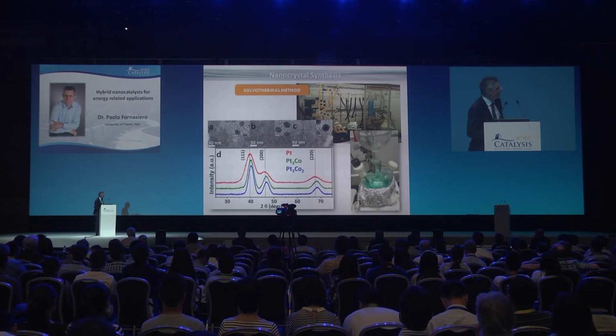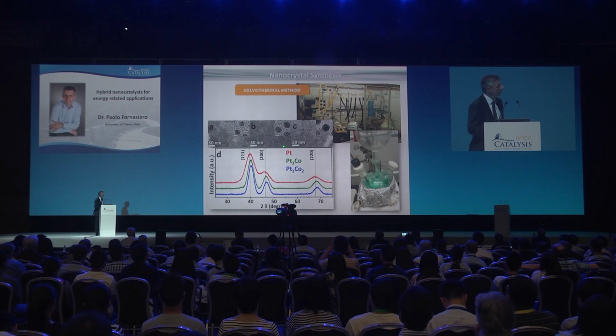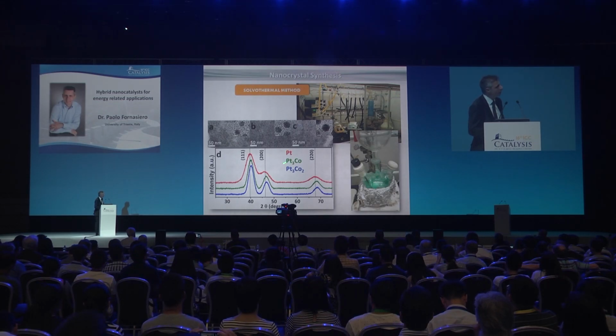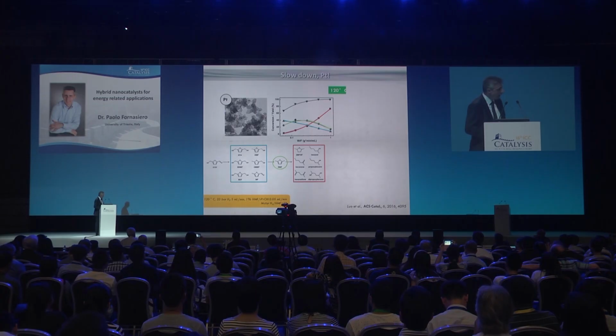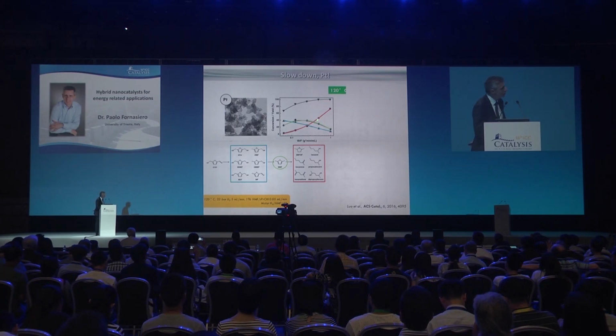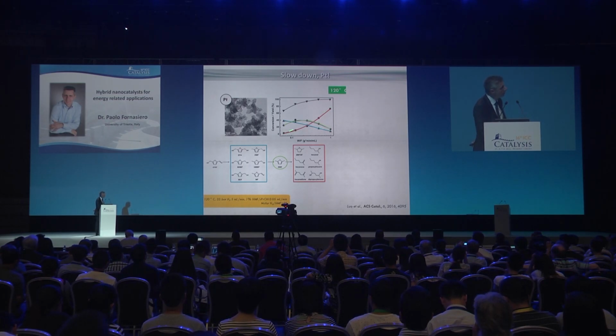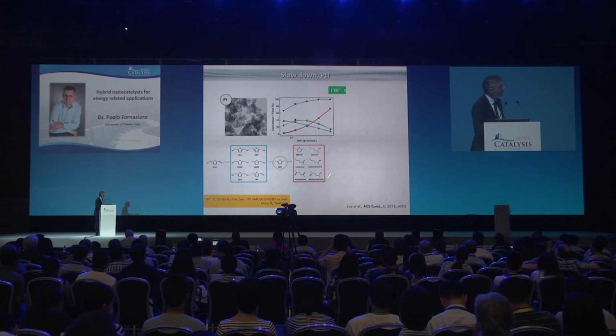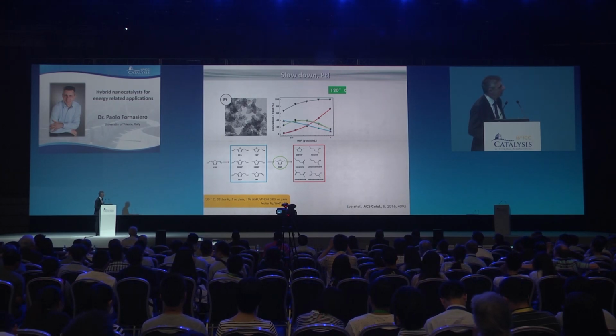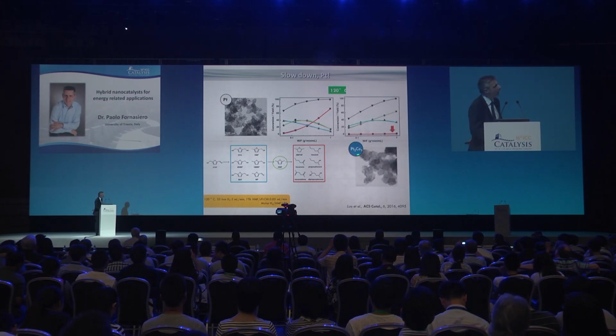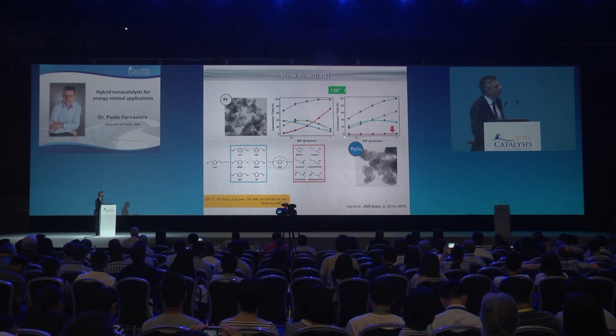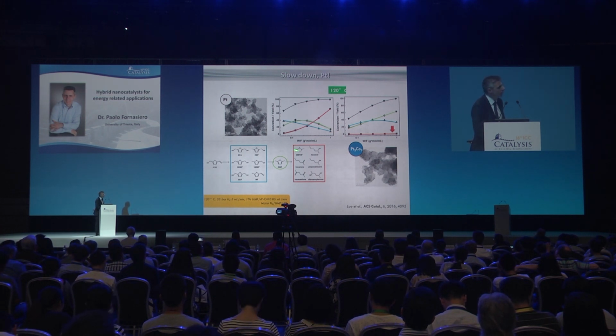Indeed we managed to prepare crystals of platinum and platinum-cobalt, of different compositions. As I mentioned, platinum is not selective. We did this in flow, and you can see that the amount of products depends on the working conditions, but still you get this sequential reaction. If you use a platinum-cobalt alloy, you get something which is really selective, and you slow down this reaction significantly.